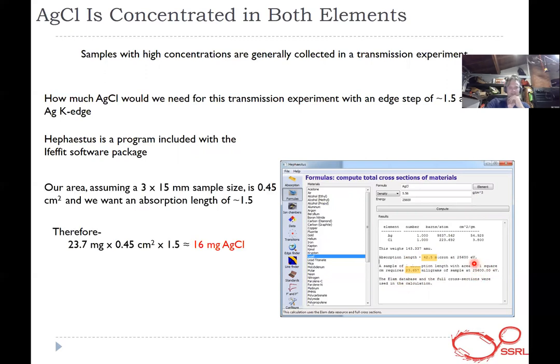So what do these numbers mean? This calculation is based on 1 square centimeter. Adam Hoffman will talk about this in a lot more detail than we will here. We have about 0.45 square centimeters and we want an absorption length of 1.5. So we take that 23.7 milligrams times our sample area, which will be defined by the sample holder that you use. This form factor varies depending on your beamline, synchrotron, and technique, so this number will change. Then times 1.5. So we'll need a total of 16 milligrams of silver chloride in a 0.45 square centimeter area to get an absorption length of 1.5.